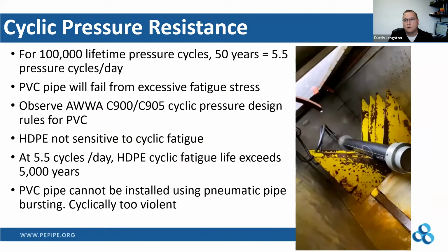The American Waterworks Association actually did a study a while back trying to find out the average amount of cycles per day that your typical water distribution system sees. If you take that 100,000 lifetime cycles allowed for 50 years, that's 5.5 pressure cycles per day allowed, and that's a 50-year life. The amount of cycles that you have in a typical distribution system is actually much greater than 5.5 per day.